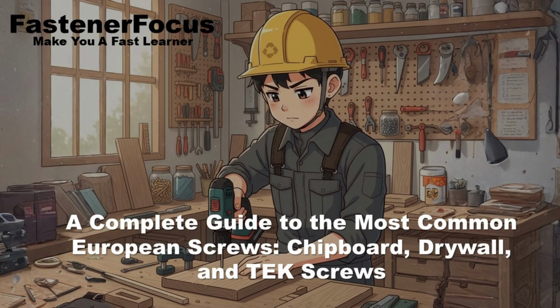It is. Residual compressive stress is essentially pre-stressing the material. When the screw is later placed under tension or cyclic loading, the external tensile load has to first overcome that beneficial internal compressive stress before the thread root actually experiences true tension. So if you do the rolling before the heat treatment? The high temperatures of the heat treatment process will relieve those beneficial residual stresses, largely negating the anti-fatigue benefit. The sequence matters immensely for the final product's ability to resist failure over decades of service.